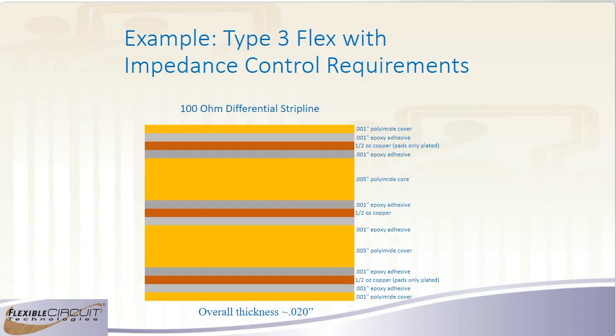And you can see you went from 6 mils in one up to 20 mils, even though electrically they're going to be very similar, but in high speed you'll get the performance you need, but you're also going to have a much stiffer and thicker circuit.